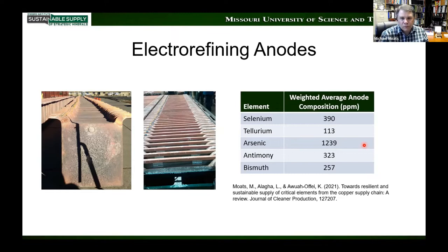So this cell looks, I think, like it's in Peru. Worldwide, I'm part of a group that surveys as many refineries as will respond to us. We're in the process of doing this again for the Copper 2022 meeting that's going to come up next year, but this data is from 2019. So the world average is a weighted average based on the capacity production of each facility that we've surveyed. You can see that we went from tens of ppm of these values, maybe hundreds of ppm in the deposit. There's not a lot of concentration really going on in the flotation circuit. But as you go through the smelter, when you get to the refinery, we've seen a significant uptick in the concentration of these elements, maybe a factor of 10 to 50, depending on the element.